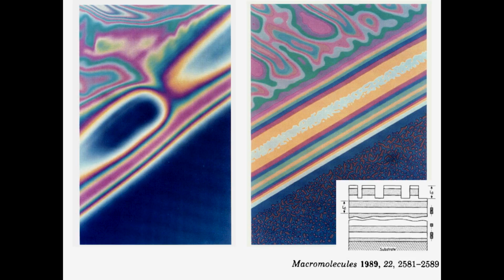This is remarkable. With your eye, you're getting resolution that's 10 nanometers or better. All right? That's pretty good. No electron microscope, nothing. This is just using a simple optical microscope. Doesn't have to be high power resolution. You see different colors that correspond to different thicknesses, etc. So it just so happens that the reason you get these step changes is that with the copolymer, you're forming these layered structures, and the thickness at any point is defined in terms of the pitch or the period of the copolymer. It's very simple.